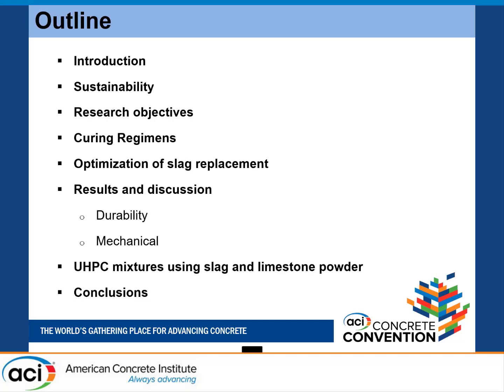Commercially available ultra high performance concrete products are highly expensive. That is the main reason for not using this important material, even with the great benefits it offers, like greater compressive strength, mechanical strength, and extreme durability. But because of the initial cost, this material is not being widely used in a variety of structural applications. So therefore, we thought of reducing its cost by using supplementary cementitious materials in high volumes.